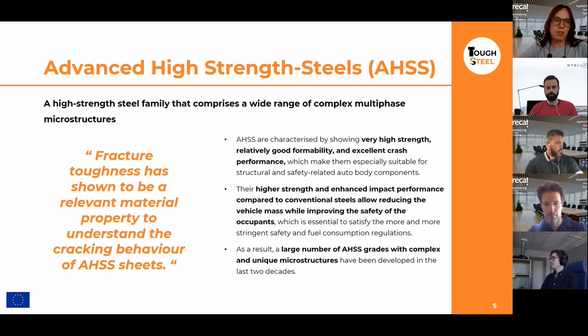But the rapid implementation of these materials in automotive has introduced new problems that are still not completely solved because of the limited ductility or formability of these advanced high-strength steels compared to conventional mild steels. This can produce crack-related issues that cannot be rationalized and predicted in the product design stage by the traditional approaches, such as the tensile test, for example, or the forming limit curve. And this hampers the use of the advanced high-strength steels and the development of high-performance parts of reduced cost using these materials.